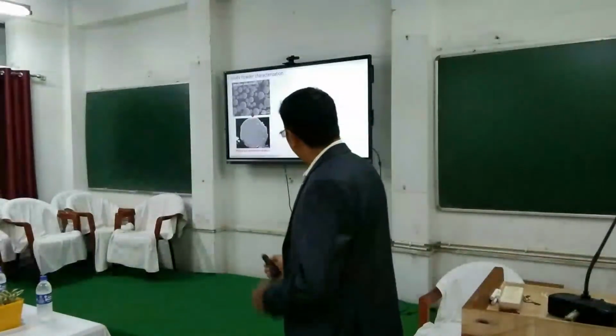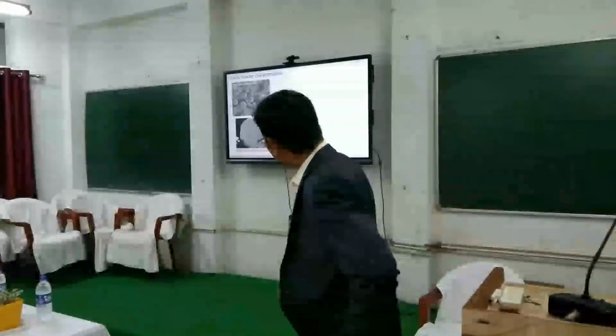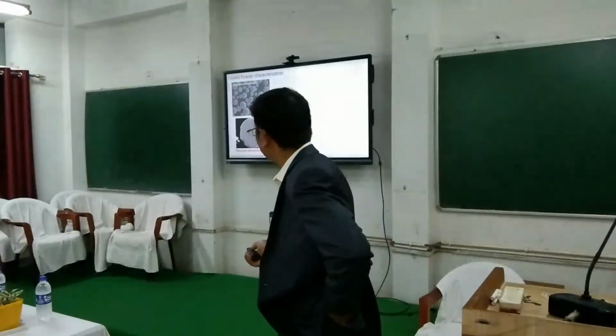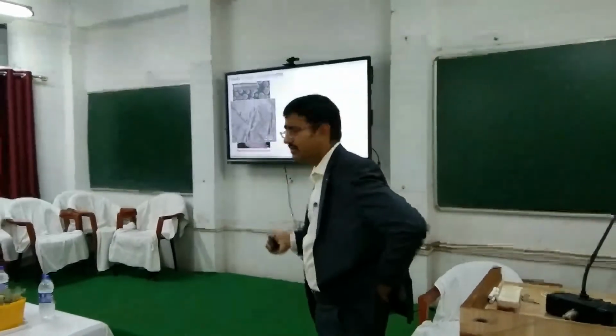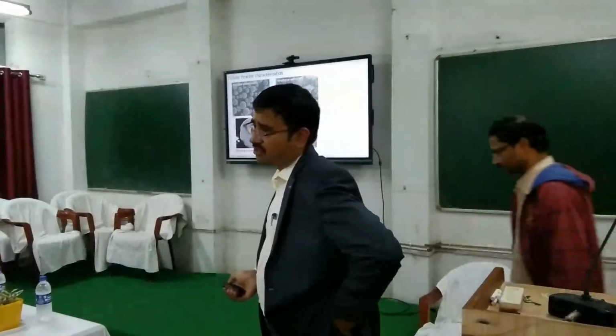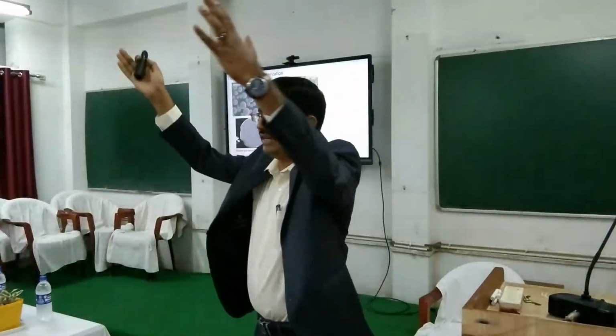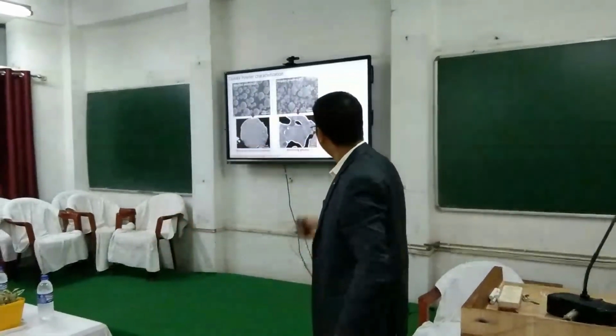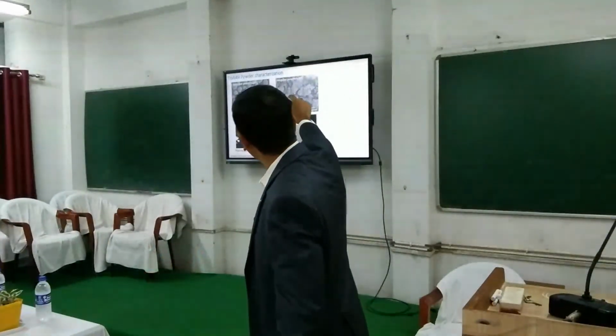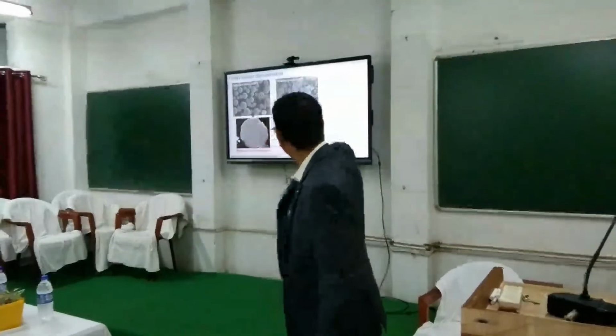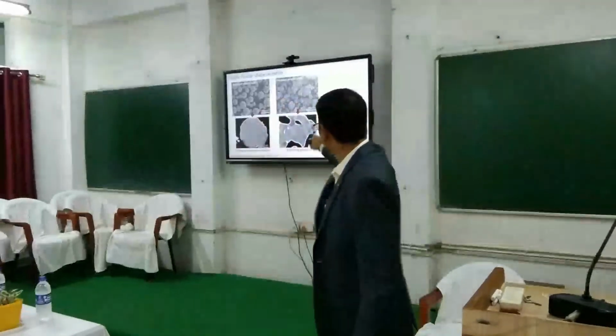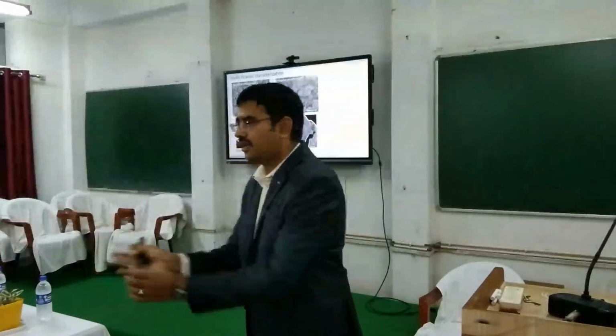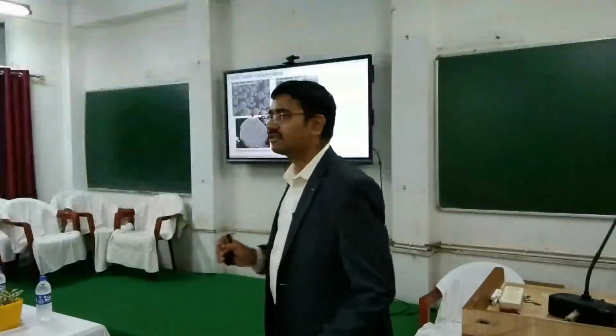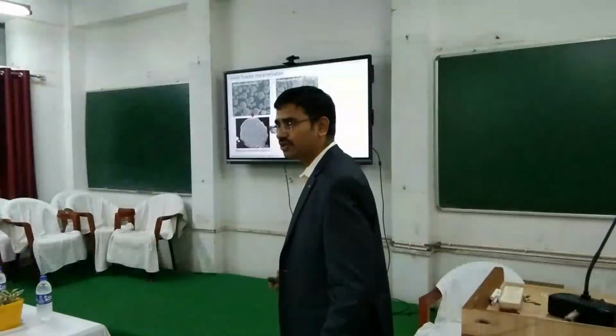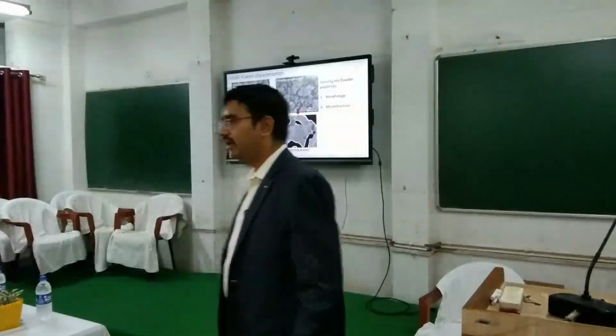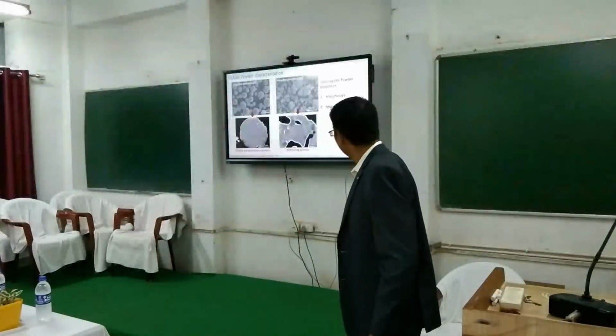So what we did basically is we tailored the microstructure of the powders. We had traditional spherical powders which we fabricated using a plasma gas atomization process, and we could see some martensite laths. We adopted a different process which is known as the Armstrong process. It's a modified Kroll process where there is no rapid heating and cooling. Basically it's a chemical reduction process, and when you use it, you get irregular morphology of the powders, and when you cross section the powders and look at the microstructure in SEM, you see a more equiaxed, grain-like microstructure. Martensite is hard to deform, whereas grain-like structures are easier to deform, and you are getting the irregular morphology also. So we tailored two properties of the powders, the morphology and the microstructure.